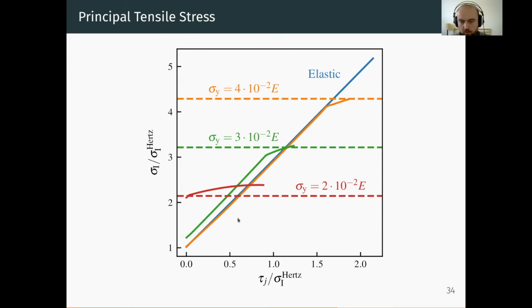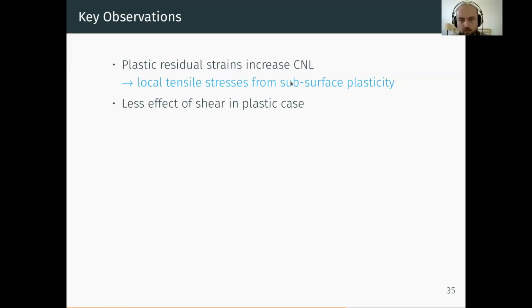And this is apparent here in the softer case, where the yield stress is the lowest. You almost have a constant behavior, kind of like what you have in hardness in indentation. So this explains why there is no real dependency on tau j for the case where we have full plastic deformations. But there's also something that's interesting to note, this initial point here. So this is when tau j is equal to 0. This is pure normal contact. As we get softer and softer, as we decrease the yield stress, we have higher tensile stresses in the system. And this explains why we had a higher crack nucleation likelihood in the case where we had a full description of plasticity, because plastic deformations introduce tensile stresses. And when those plastic deformations reach the surface, the effect of those additional tensile stresses is the largest. And so, we have subsurface plasticity that introduces tensile stresses and increases the crack nucleation likelihood.